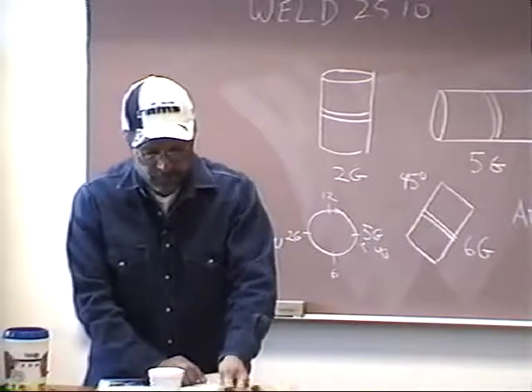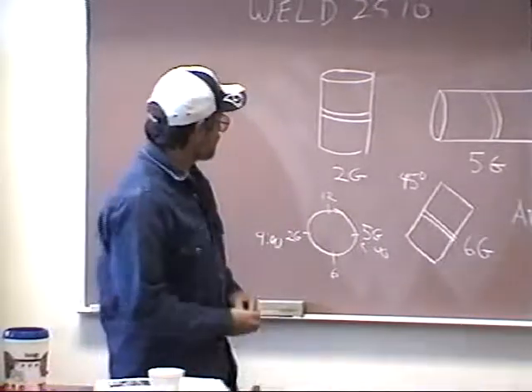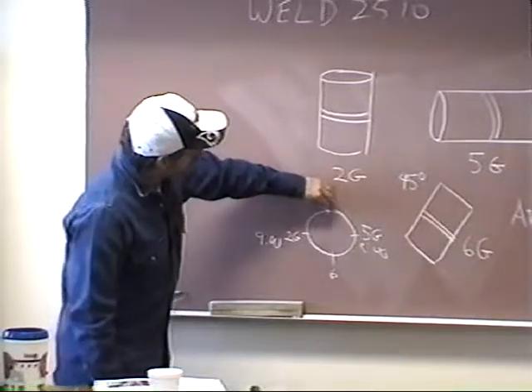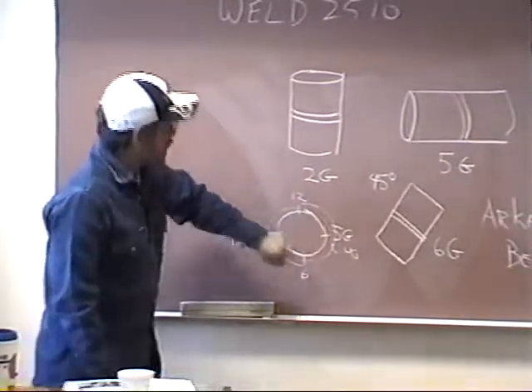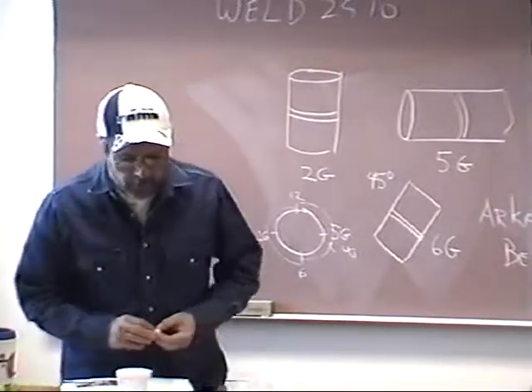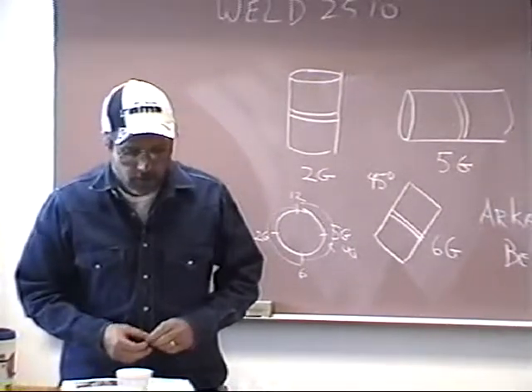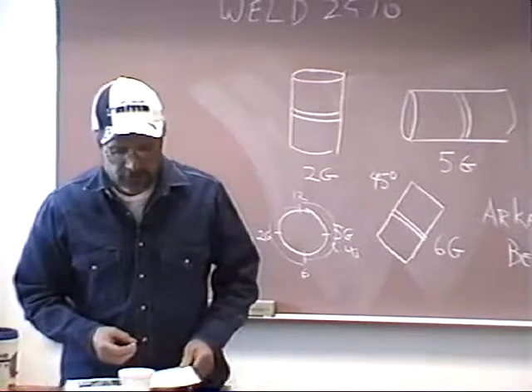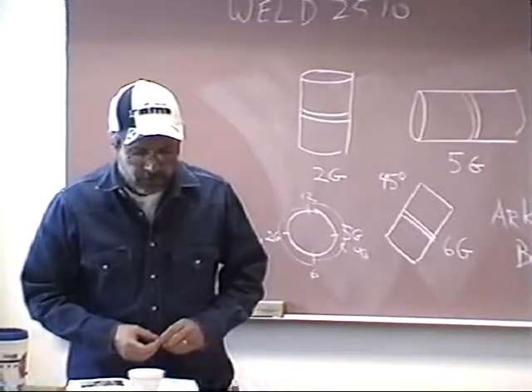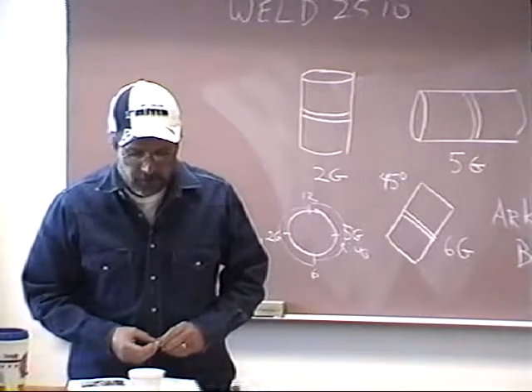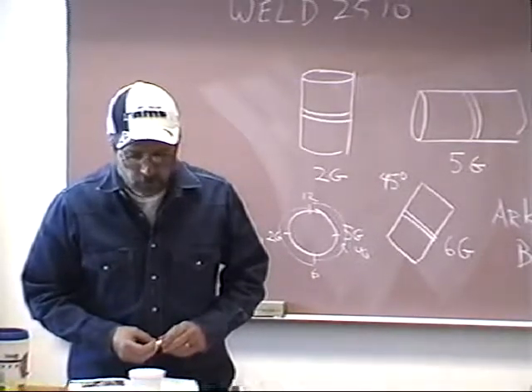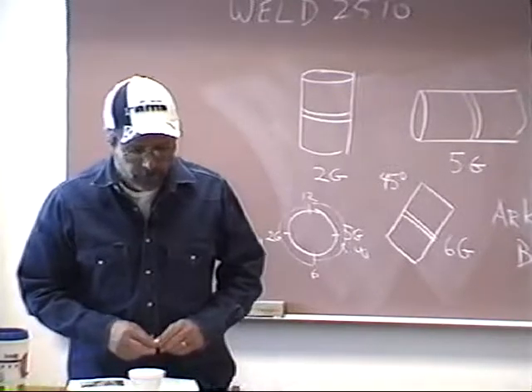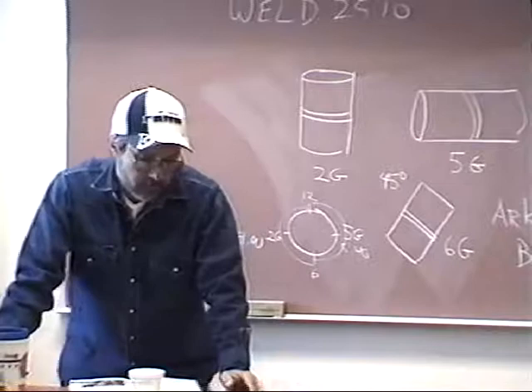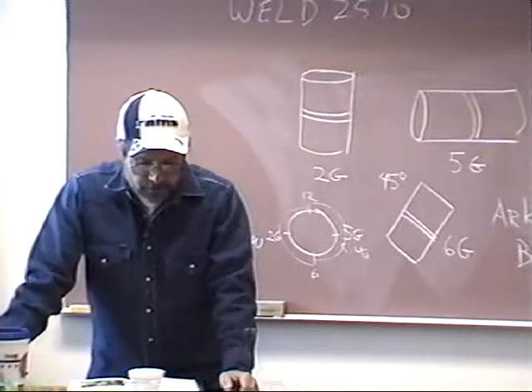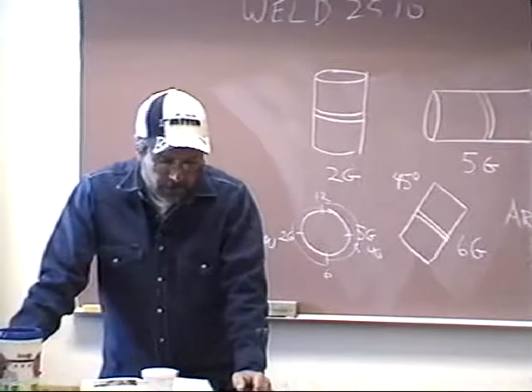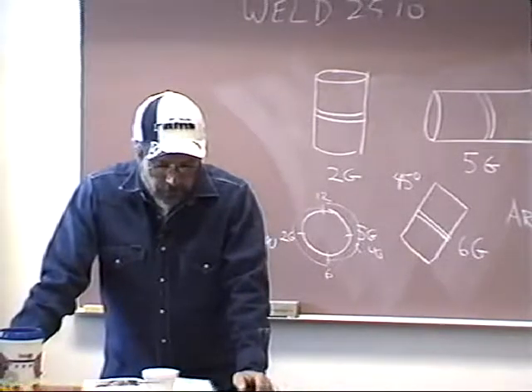Then you will go back up to the top, start at the 12 o'clock position again, and weld downhill once more. So when you're welding in the downhill position, you're going to start here, weld down, start here, and weld down. Downhill pipe welding is used primarily to weld thin wall mild steel pipe having a wall thickness of 1/8 to 5/16 of an inch thick. The relatively thin wall of the pipe retains the heat longer than thick metal would. This causes the metal in the weld area to cool more slowly if the speed of welding and the heat input are the same. Slow cooling is desirable because a softer and more ductile grain structure is then obtained in the weld and in the weld area.